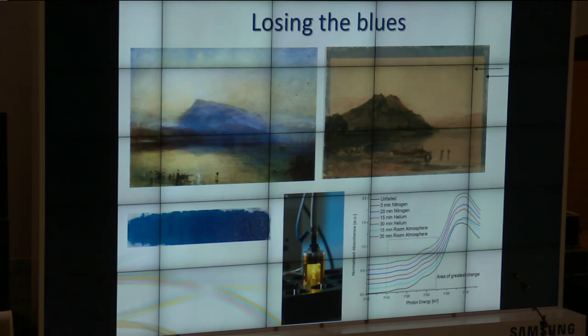So if you want to display the picture to the public, it can't be in the dark. So yes, you try and reduce the light levels, but there's still some light. So you also want to take away the other influences. So the strategy that was developed was to display the paintings in a special kind of frame with glass, under vacuum or under a gas that didn't contain oxygen. And early work indicated that this was a good strategy in general for preserving pictures, except that Prussian blue in the early measurements appeared to fade faster in the absence of oxygen, which was a very counterintuitive result.